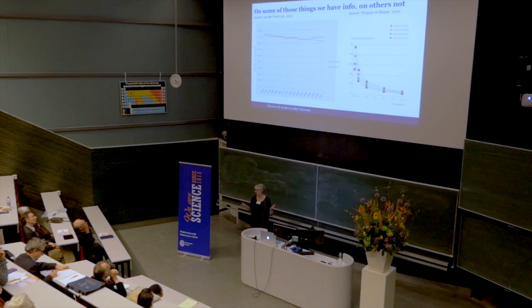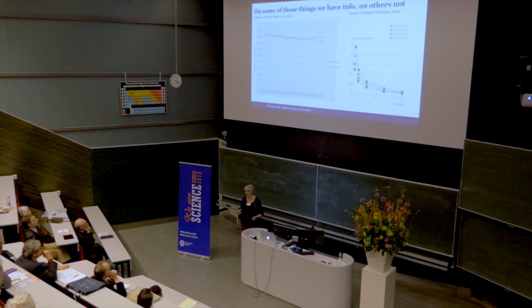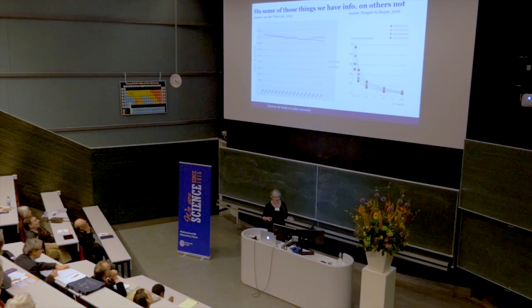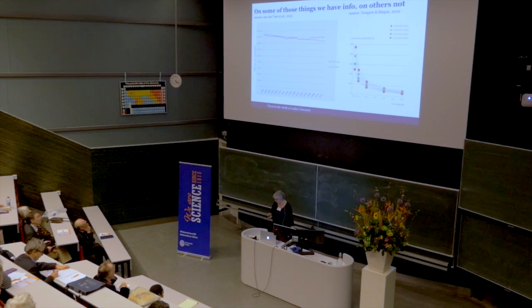And that's not because the industry has done nothing in the meantime to clean up their act. It's just because, again, of the laws of nature. It takes a lot of energy to separate the aluminium from the oxide. What goes into the smelting is aluminium oxide, alumina. And if you have to pry that apart, you just have to overcome the chemical bonds. And that takes energy. So this hasn't improved a lot and probably will not improve a lot. So it's a given for our future.